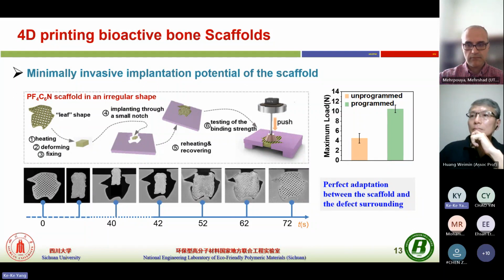We first print the scaffold with an irregular shape, then program and form it into a small size, so you can implant it through a small notch. We can then trigger its recovery by heating, and it perfectly adapts to the defect surroundings, with binding strength greatly improved compared to the unprogrammed ones.